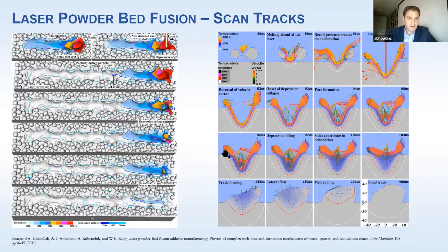All right, so what we're looking at here is a scan track. So a simulated scan track on powder. This is at 240 microseconds after the laser comes on. This bottom one is at 670 microseconds. So as the scan path is to the right, as you can see here, as the laser moves to the right, you actually end up drilling a hole in the substrate, the metal below the laser.